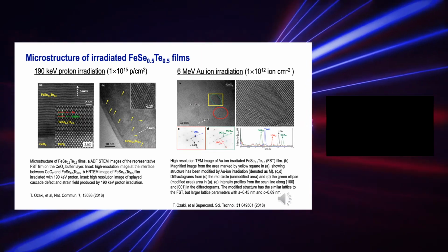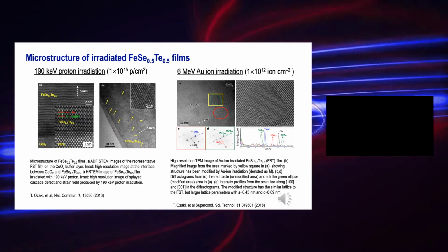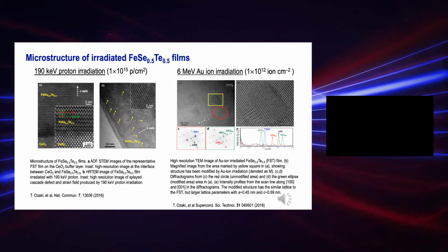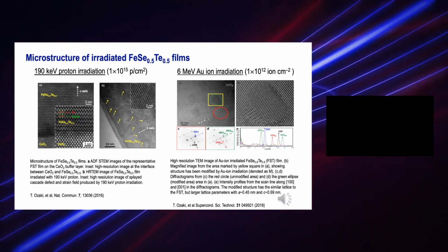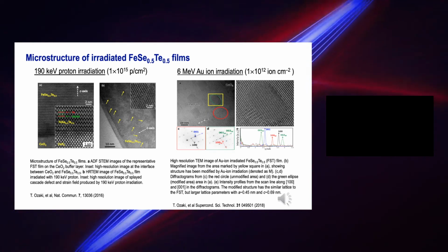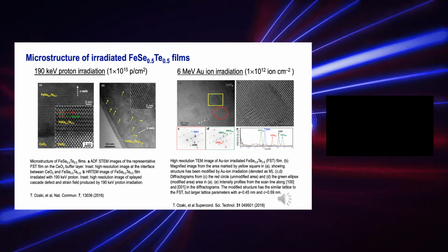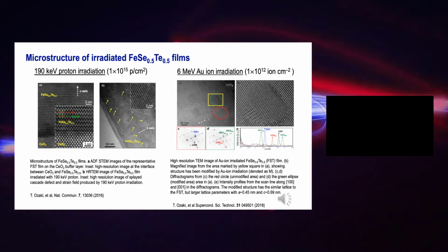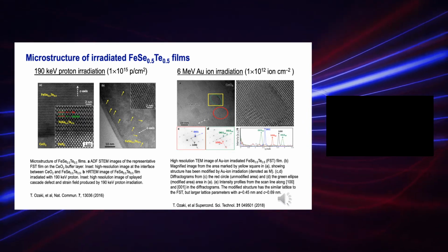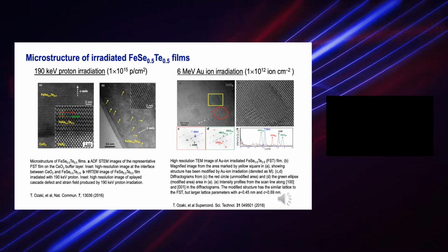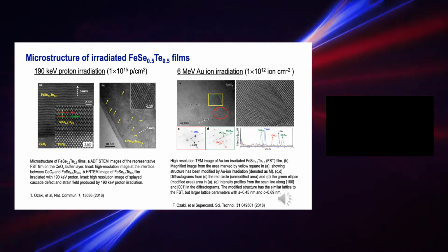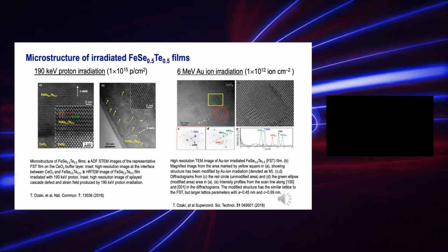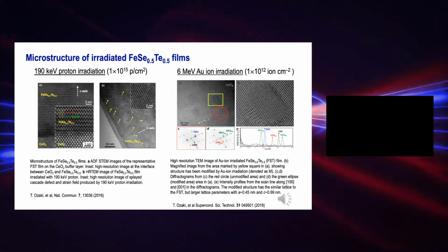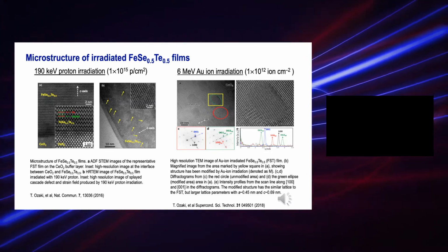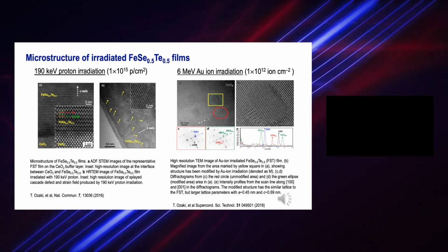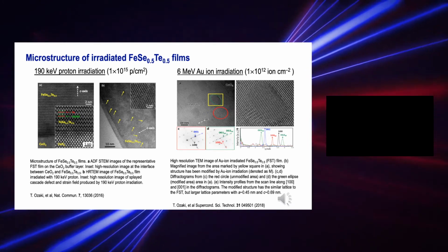Now, if you have low energy protons, you will need a higher dosage. For instance, in this one, to show the effect, we go all the way to 10 to the 15th protons per centimeter square. For the high energy gold ions, you don't need that much dosage because the defects are already big. If you put in that much, 10 to the 15th, you basically cover the whole thing. So in this sense, only 10 to the 12th ions per centimeter square would be sufficient to put enough defects in the films.